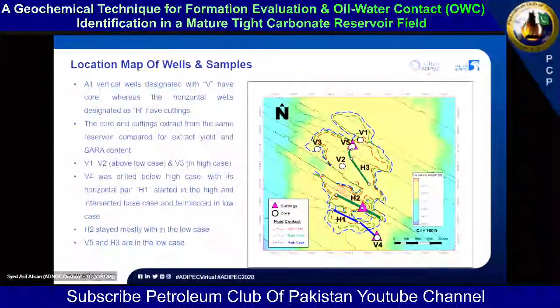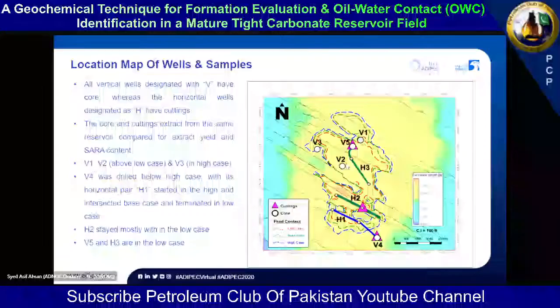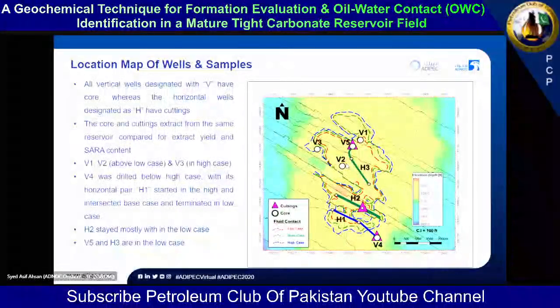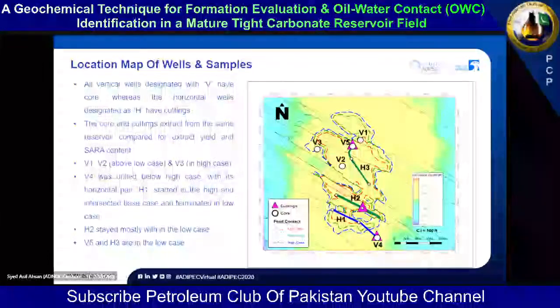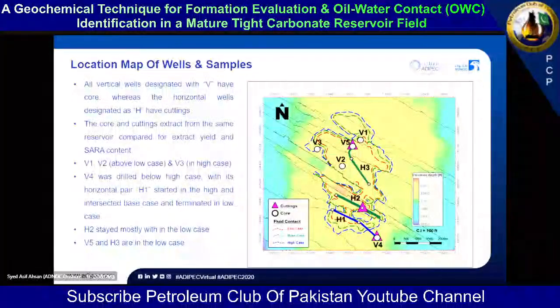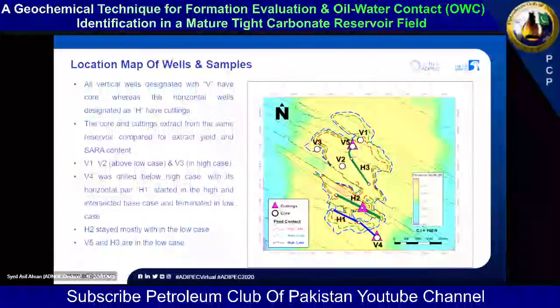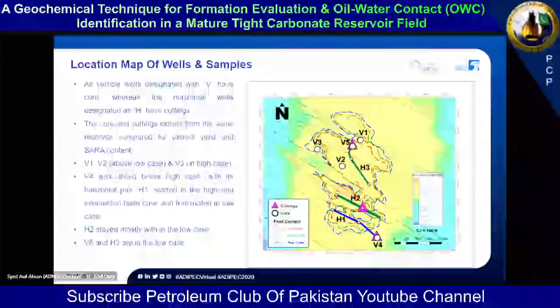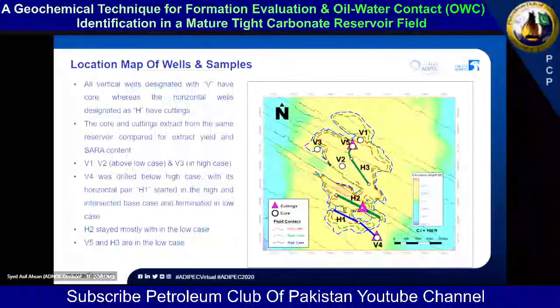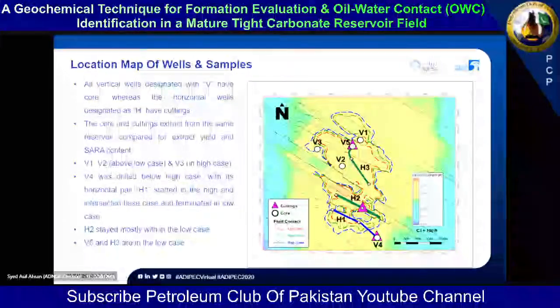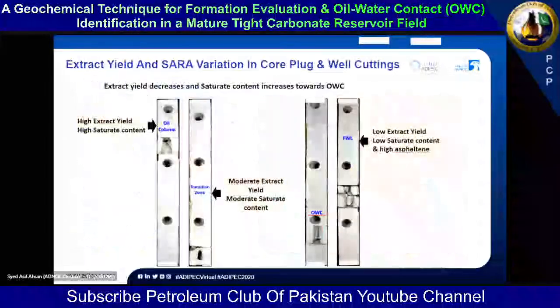So you see that V5 is also drilled within the low case, and it has a horizontal producer as well. V2 was drilled within the low case, and we will now be seeing how these well locations with respect to low case, base case, or high case, or below high case, for example, the V4 well is drilled below high case, reflect in the core and cuttings. Because we have core plugs available from the vertical wells, and we have well cuttings available from the horizontal holes. So we'll be seeing how the extract yield and SARA composition conform to our understanding of the low, base and high case in this field.